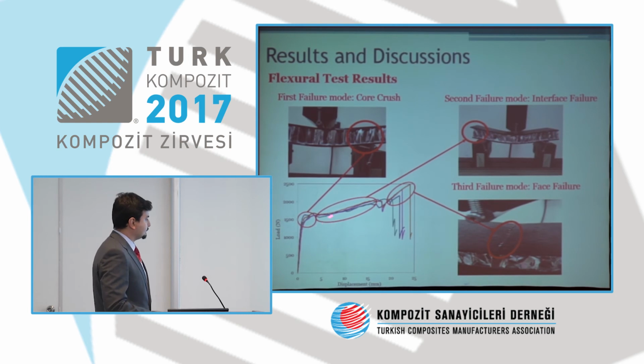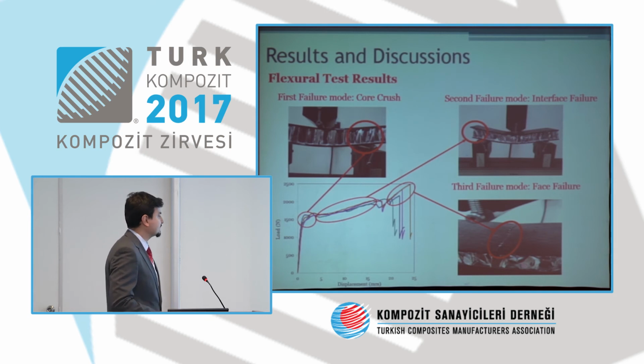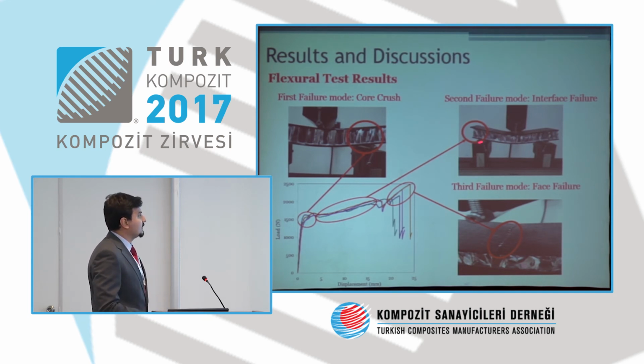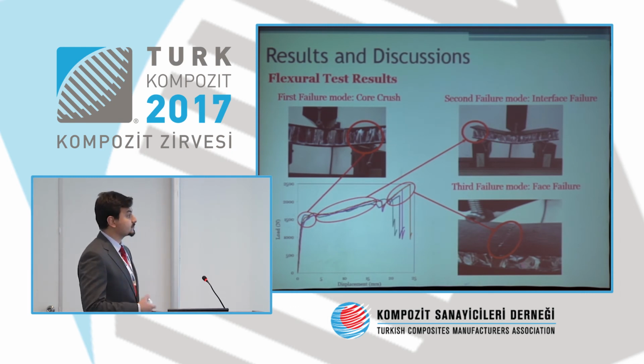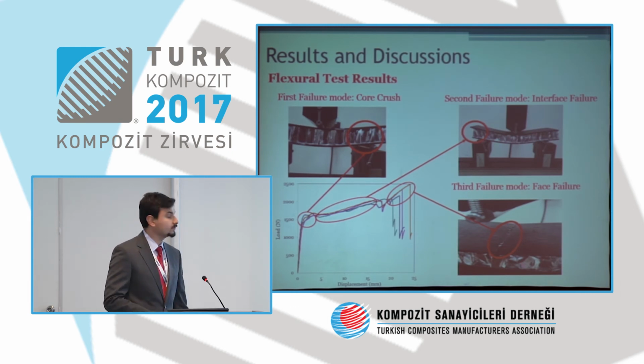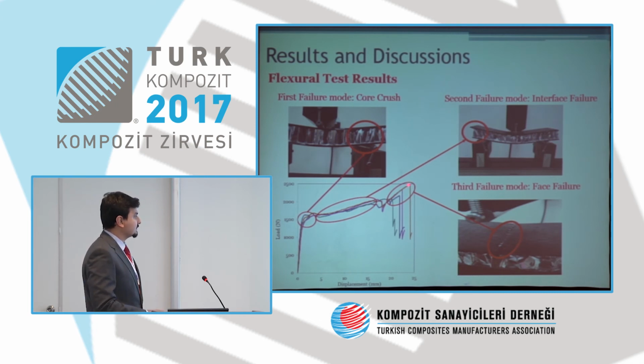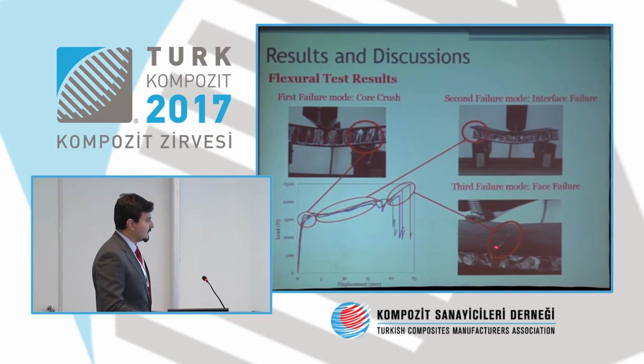Then a linear path follows this with a low tangent. Here we obtained the interface failure at the edges. As you see here, it occurs due to high shear load. And the last failure mode is the face failure. And here the load is increased dramatically, and the failure is here.